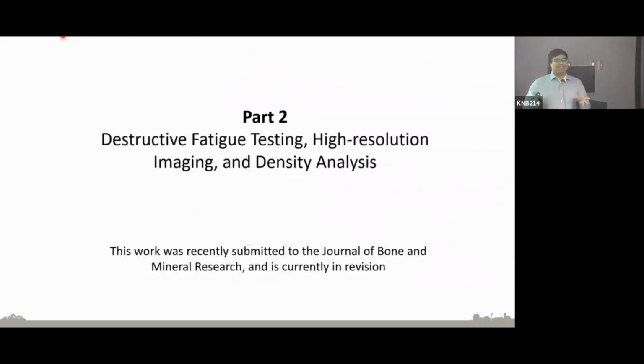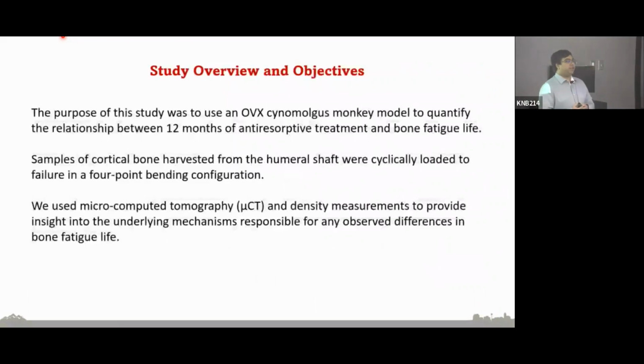So with all that said, let's jump into what I think is a really exciting part, which is our fatigue analyses in part 2. The general purpose of this part of the study was to use an ovariectomized, again, the same cynomolgus monkey model that we already used, but this time we were looking at bone fatigue life differences. We did that by harvesting small samples, matchstick-sized pieces of bone, and loading them cyclically until failure in a bending configuration. We also did some more supporting measurements to try and understand why we were seeing what we were seeing. So we did, again, some more high resolution micro CT, as well as some traditional, what I'm going to call manual density measurements, to really look at what's going on.